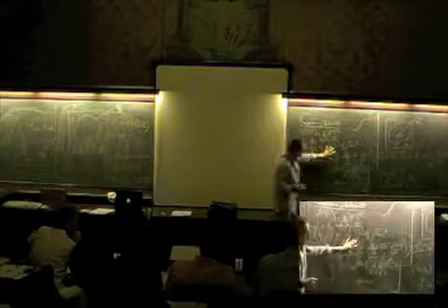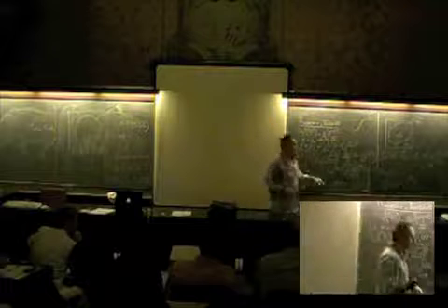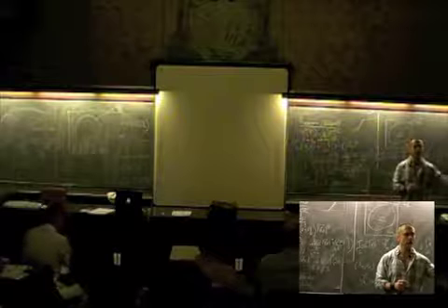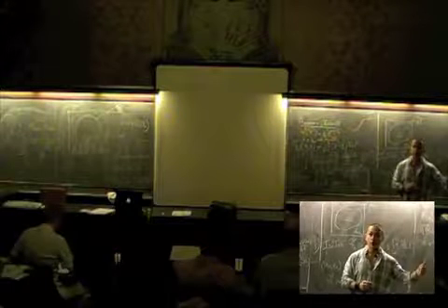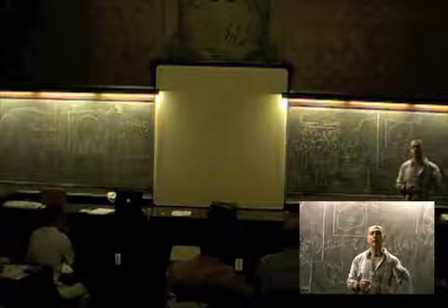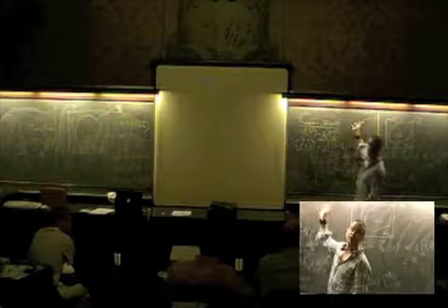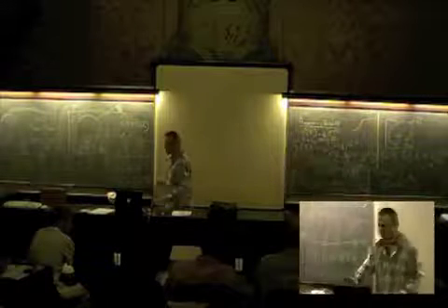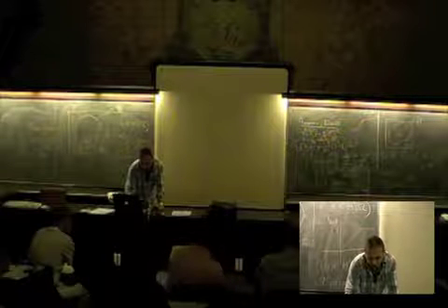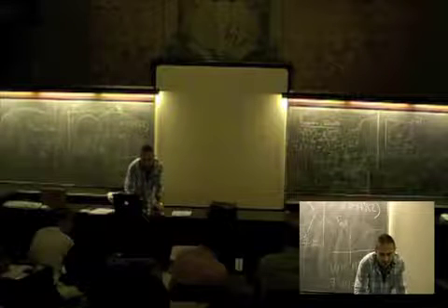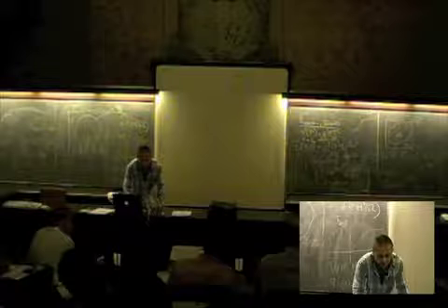Yes, so, okay, and then how do you advance? Well, you advance by deciding that once V epsilon was 10 to the minus 2 at a given time step, you put it to 0, and it'll stay 0 for all future times. So you essentially increase the area where V epsilon is 0. That way you enforce irreversibility. All right. So colors are going to be level sets, or sub-level sets, of V epsilon.